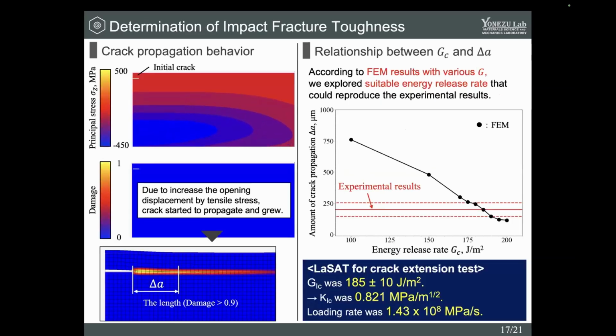This is an example of FEM result, wave propagation behavior and crack propagation behavior. As shown in this animation, we observed cracks started to propagate as the opening displacement increases due to tensile stress wave. In order to determine impact of fracture toughness, we explored suitable energy release rates that could reproduce the experimental results.